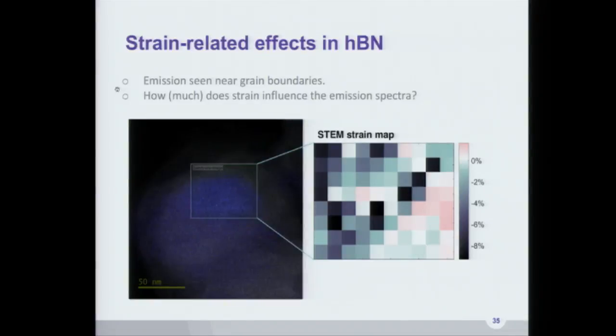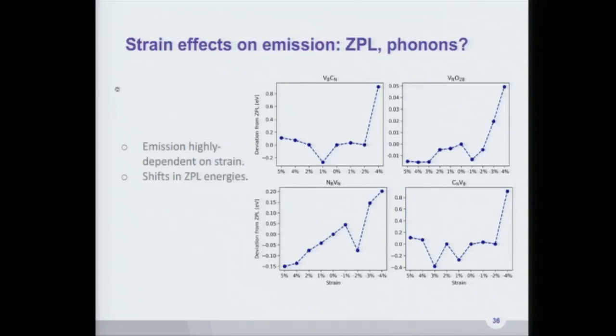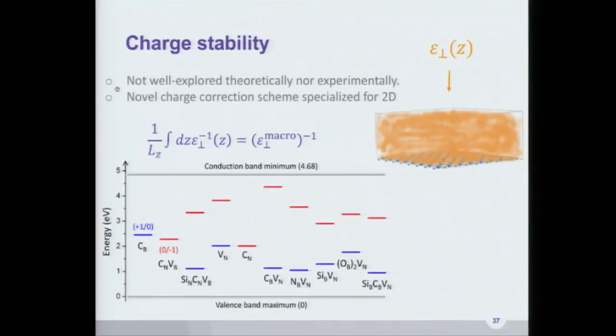So we are predicting the strain maps that hopefully should match up with the strain maps that Jen and her crew are measuring. And to see that if we know which defect it is, we know how it varies with strain, we know how the sidebands vary, we should be able to fingerprint, right? So you should be able to do something similar to the way people do image analysis to figure out who's who. You have a set that is predicted, and maybe the set that's measured, and say this is a combination of two things. So maybe there's a cat and a dog simultaneously in the picture, not just a cat or a dog, and that's why you're seeing these two different kinds of features all at once.